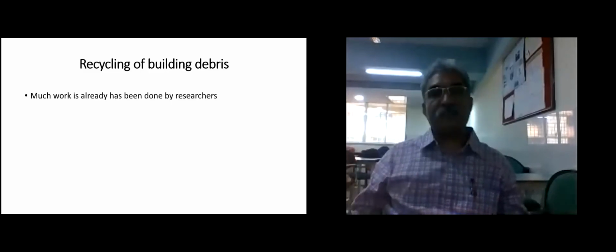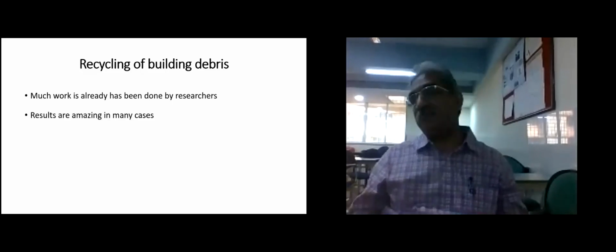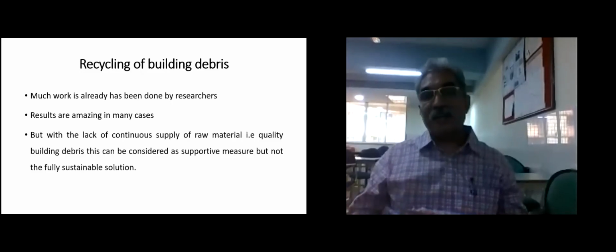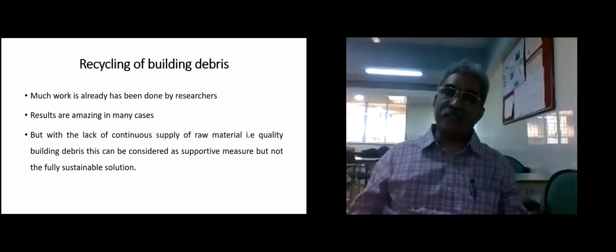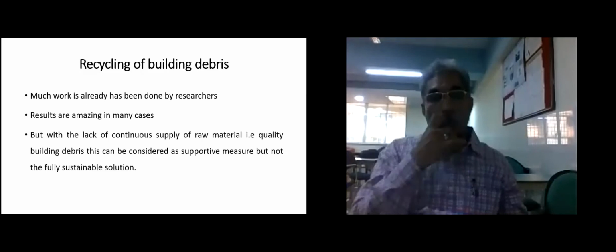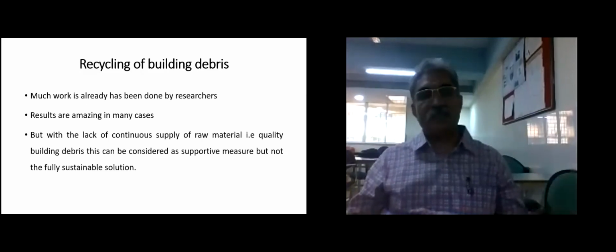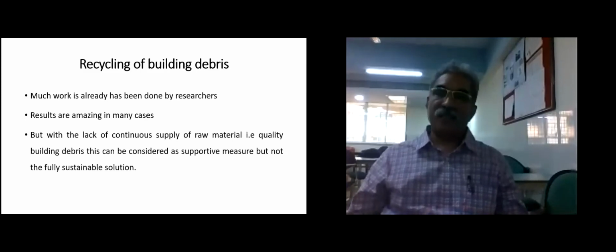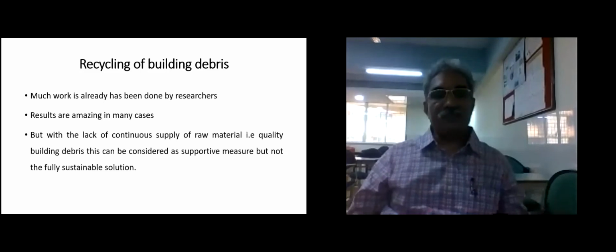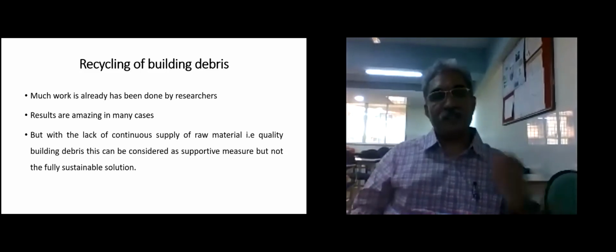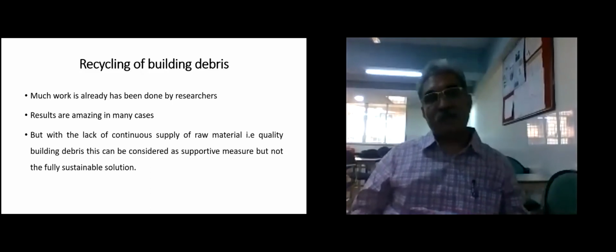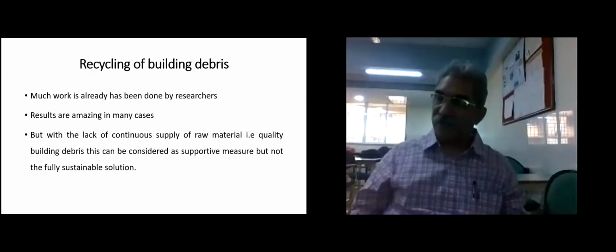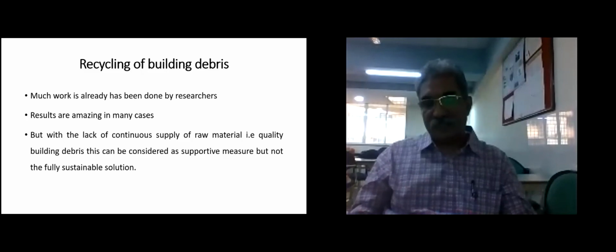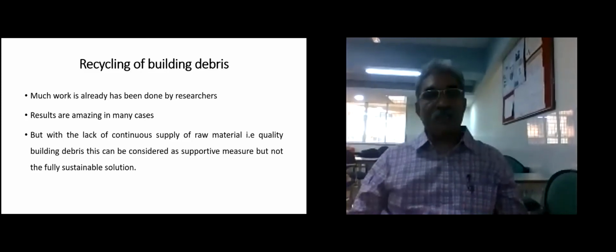But much, as I said, much work has already been done. Results are amazing in many cases, but with the lack of continuous supply, because all the time you will not get the raw material, and you will not get the quality building debris. Sometimes the building may be deteriorated to the maximum extent, so that debris may not be very good to use in such cases, for whatever the motive we are working with. So it will be useless for us, and this can be considered as a supportive measure, but not a fully sustainable solution. So recycling of building, we have also made some experiments, and the results were amazing, but still we concluded that it cannot be the final solution. It can be supportive.